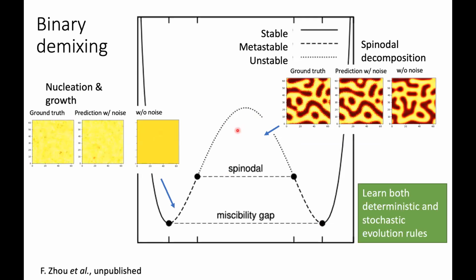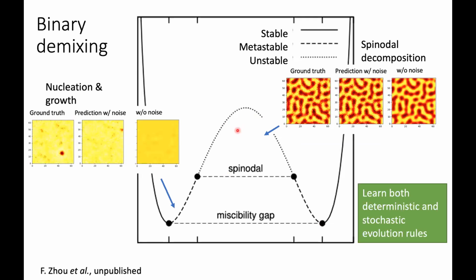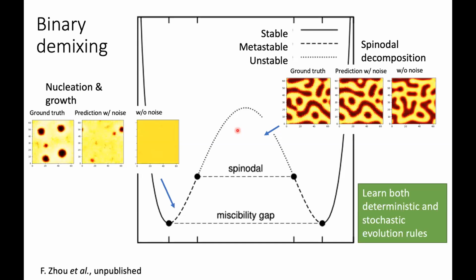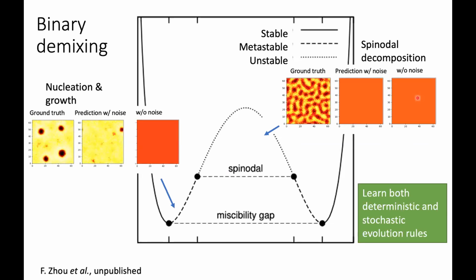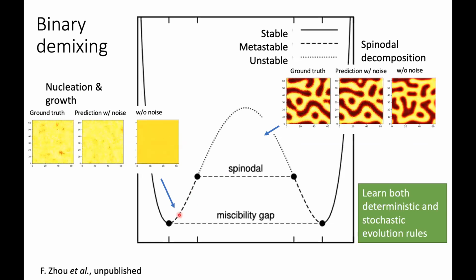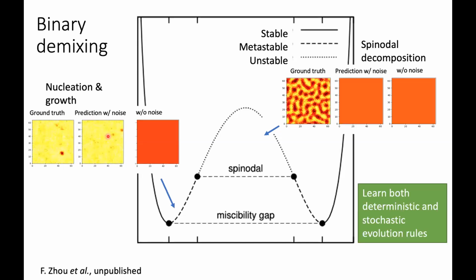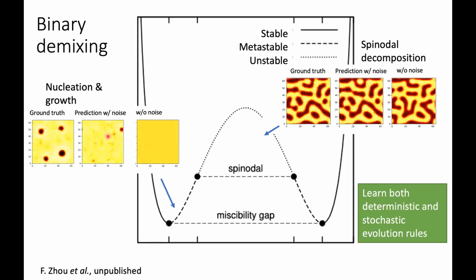Within the unstable region, the phase separation goes through the spinodal decomposition mechanism. And if you only learn the deterministic driving force, we can still sort of reproduce this mechanism. Whereas in the metastable region, the phase separation goes through the nucleation and growth mechanism. And without fluctuations, the system becomes infinitely metastable and nothing happens. Whereas the introduction of proper fluctuations allows the emergence of a nucleus, and this system can go through the proper nucleation and growth mechanism.